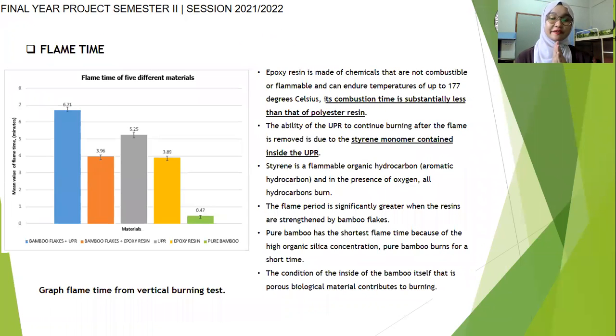Next, for the flame time, this is the graph of flame time from the vertical burning test of 5 different materials, and you can see there, bamboo flake UPR has the highest, the longest flame time. Pure bamboo has the lowest flame time because it has a high organic silica concentration. Therefore, it has a short time. However, the condition inside the bamboo itself, that is porous, contributes to the burning.